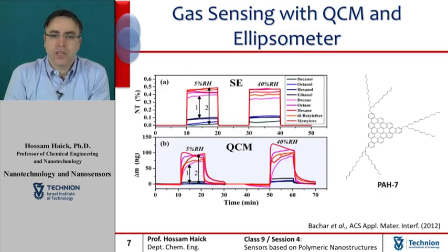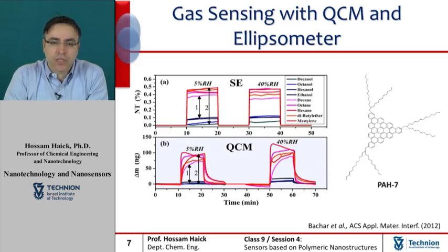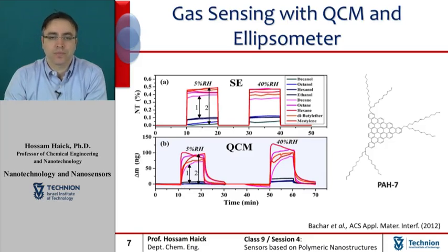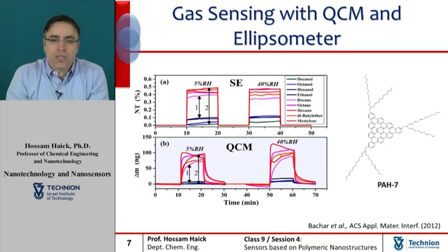Indeed, changing the sensing layer from PAH6 to PAH7, meaning changing the shape of the corona from 60 carbon number and triangle shape, and side chain characteristics, enable excellent sensitivity to nonpolar analytes compared to polar analytes in a setting of 5 to 40% counteracting relative humidity. This could be related to the interaction between the nonpolar analytes with the hydrophobic part of the examined PAH. This is a most important result as nonpolar analytes are usually more difficult and more challenging to detect than polar molecules.